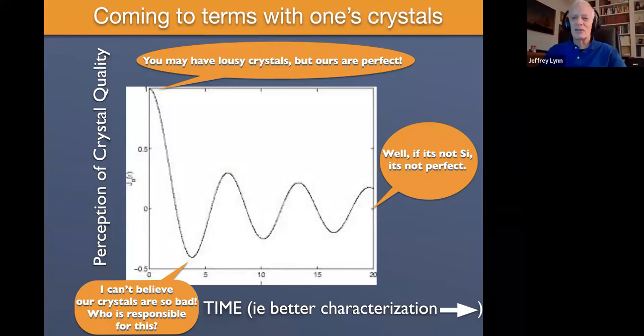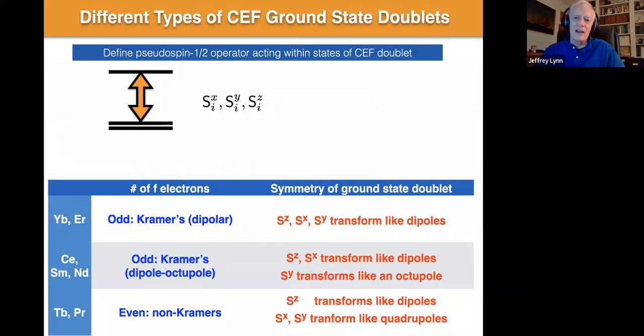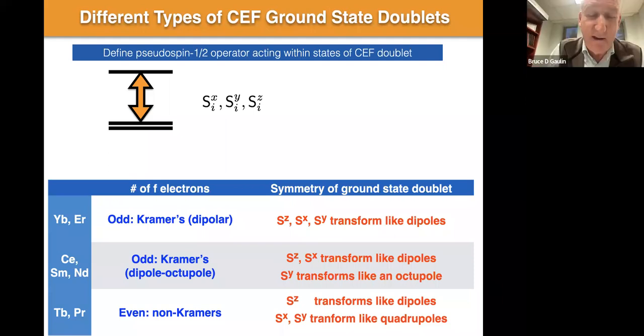Well, so we studied, with Kataoka, terbium titanate, which is a quadrupole ordering system. You already mentioned that the terbium has two components, a quadrupole and a dipole, but what we found, or he found, is that the ordering is very sensitive to the oxygen concentration. So really tiny changes in the oxygen concentration can change that. So I was wondering if you have studied that in any systematic way to see the change in the concentration, for example, this extra diffuse scattering in the stannate.